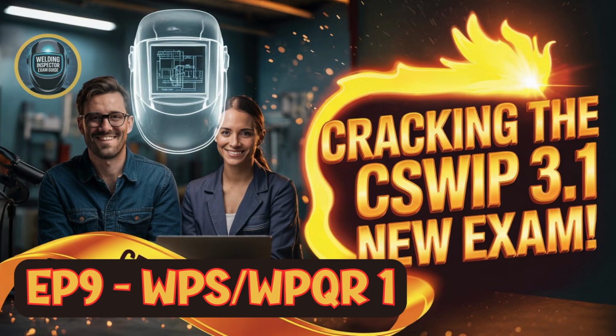Yes. For instance, it might be something like 0.7 times the test thickness up to 2 times the test thickness for a single run weld, but the specific range depends on the standard and details. Go outside that and you're in unproven territory. The type of current is also critical. AC only qualifies AC, DC polarity cannot be changed, and pulsed current only qualifies pulsed. So stick to the electrical settings precisely. Precisely. Additionally, the preheat temperature used for the test sets the minimum allowed preheat temperature for production. You can go hotter, but not colder.